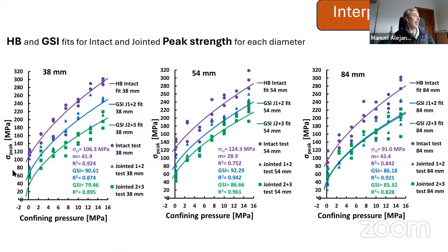So here we have the results obtained for each diameter, and we can see that for peak strength, the results obtained decrease with the increasing level of jointing. Something that is clearly remarkable is that for 84 millimeters, for large diameters, the level of jointing has less effect on the peak strength. So when we increase the diameter, the effect of the level of jointing tends to decrease.